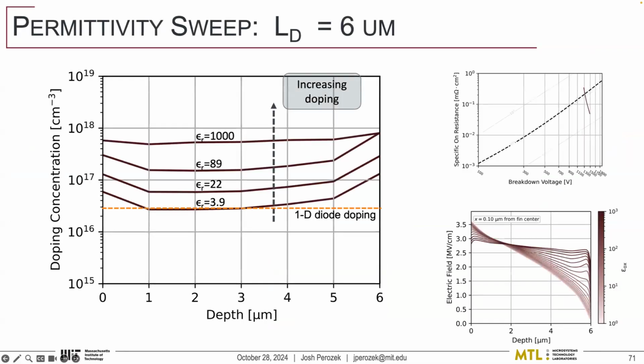If we look at what these solutions themselves look like, we talked about the doping profile not necessarily being uniform. It turns out a U-shaped profile is key for these medium dielectric constant materials. As you go to something with a permittivity like 1,000, something that's never really been demonstrated, it can become flat. But as we're trying to squeeze all the performance we can out of it, we need to tailor that doping profile to be optimal, which we're able to do there.